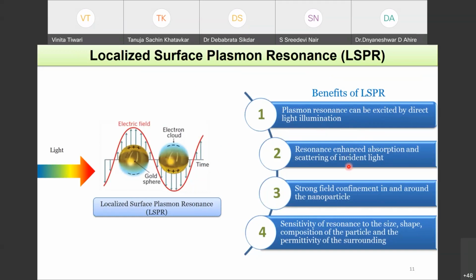The other one is resonance enhanced absorption and scattering of incident light. So you can have a much larger scattering cross-section or absorption cross-section of your nanoparticle than their geometric cross-section. You can obtain very strong confinement of electric field in or around the particle, and this resonance is sensitive to the nanoparticle's shape, size, composition, and the permittivity of the surrounding.